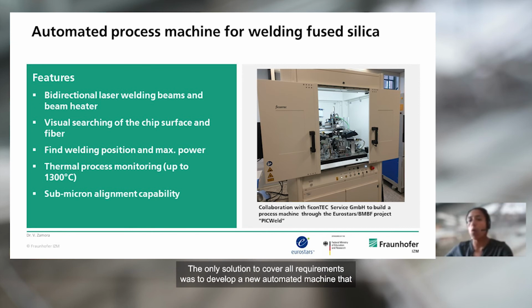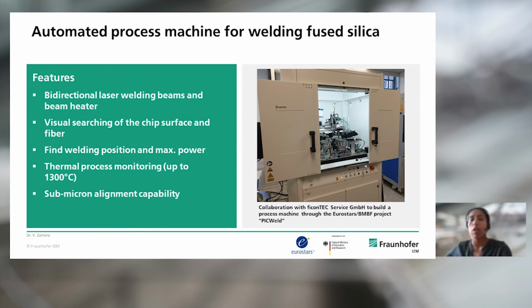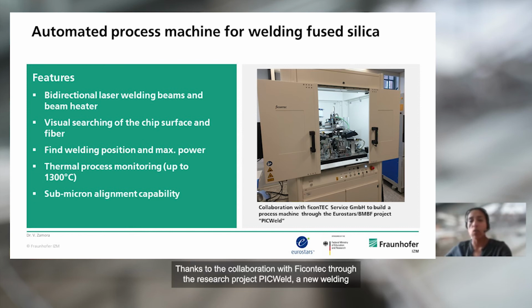The only solution to cover all requirements was to develop a new automated machine that can control the process with high precision and at the same time ensure a safe handling of the integrated waveguides and fibers. Thanks to the collaboration with ficonTEC through the research project PICWeld, a new welding machine was produced and has the following features. Bidirectional laser welding beams and beam heater, visual searching of the chip surface and fiber, routines to find welding position and manage power, thermal process monitoring using a camera system working from room temperature up to 1300 degrees Celsius, and of course submicron alignment capability.